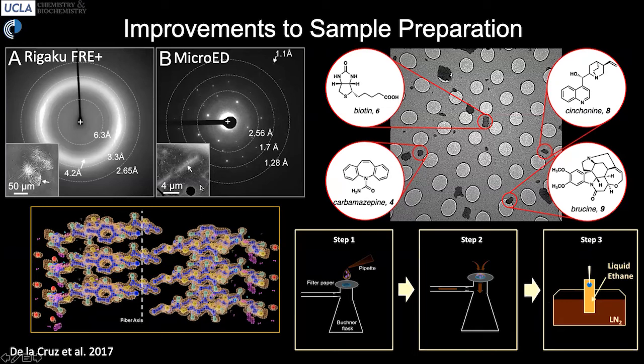And so some of the methods are sample preparation methods that we've adopted or developed. They include procedures as simple as exposing lyophilized powder of your material onto a grid and then diffracting with the electron microscope, or drop casting and pulling vacuum before freezing, or treating a suspension of molecules or a powder of molecules, or whatever it may be, as a very sensitive system, and plunge freezing it using liquid ethane, much like folks in conventional cryo-EM setups do, and then transferring that in a frozen hydrated state into the microscope and collecting data from it in that state.